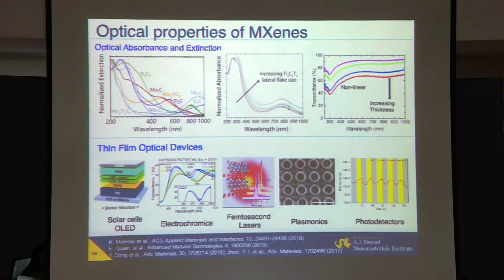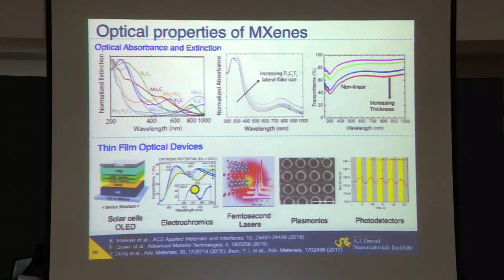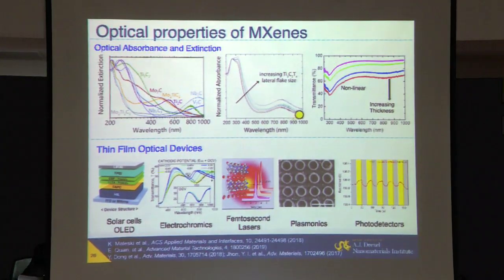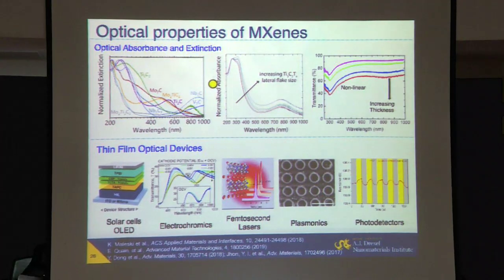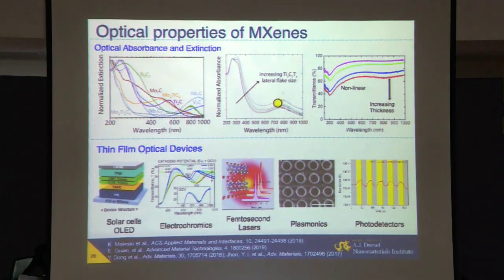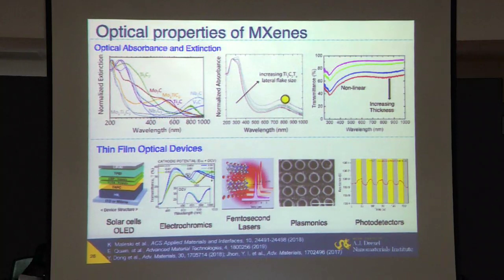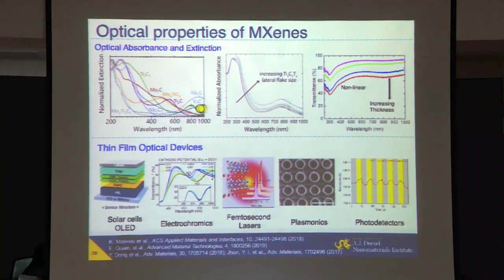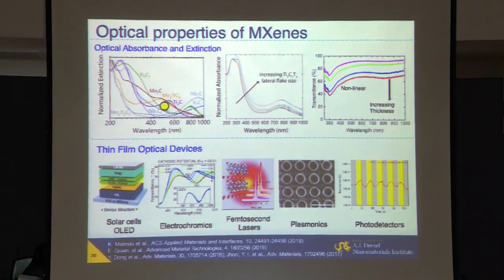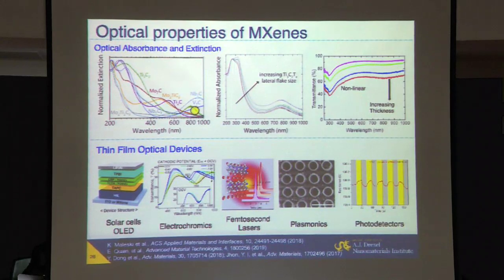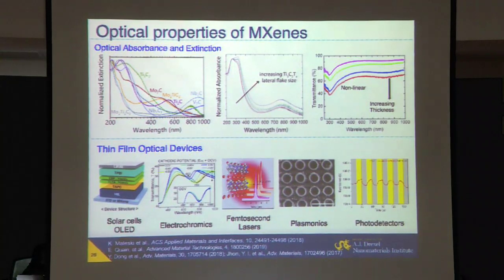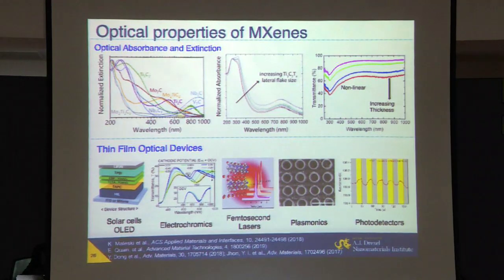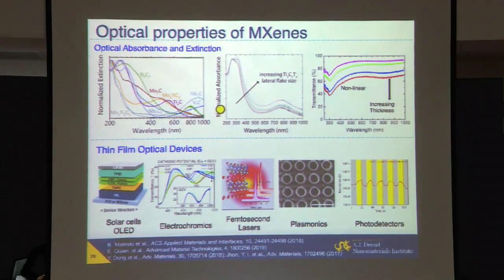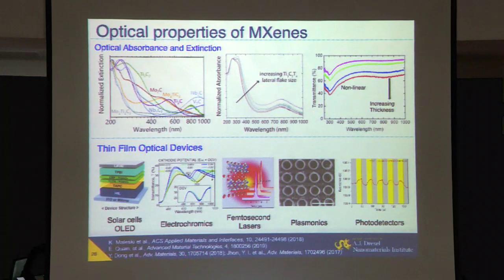But what is also important, they have very exciting optical properties. I mentioned briefly in the beginning that it's actually metal, but metal with tunable properties. If you look at this UV spectra, you will see absorption peaks. In particular, this one is a plasmon resonance in titanium carbide Ti3C2. But you see for different compositions, you will see plasmon resonance in different places. And this actually gives different colors of materials. Moreover, for some of them, they will go much further into the infrared range beyond that.